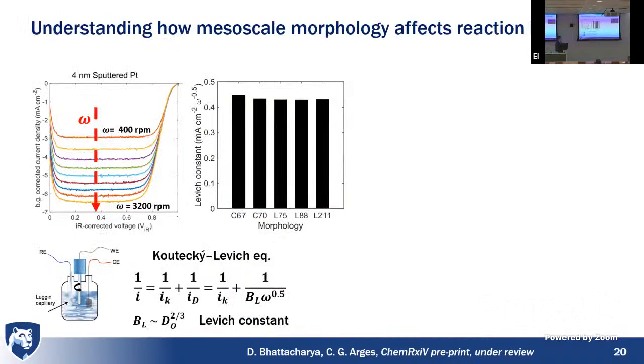There's a lot more here that I'm not going to go into in great detail, but we were curious to know whether the mesoscale morphology could affect the diffusion of oxygen through the structure. How would we know that? We can use the Koutecký-Levich equation. In this rotating disc electrode, you have a glassy carbon tip on the shaft, and you can rotate the shaft quickly. As you spin the shaft faster and faster, you get higher and higher limiting current densities. The measured current, 1 over the current, is equal to a contribution from the kinetic current and the diffusion current. We can do this analysis to estimate the Levich constant.